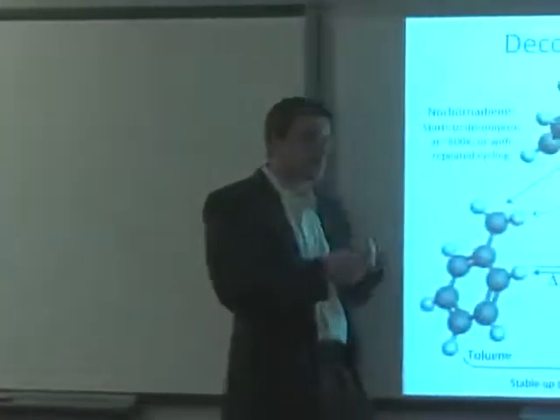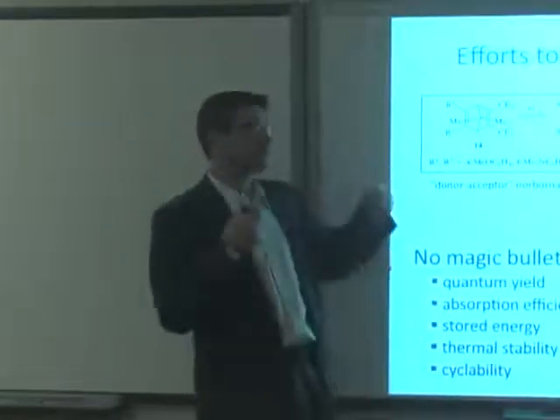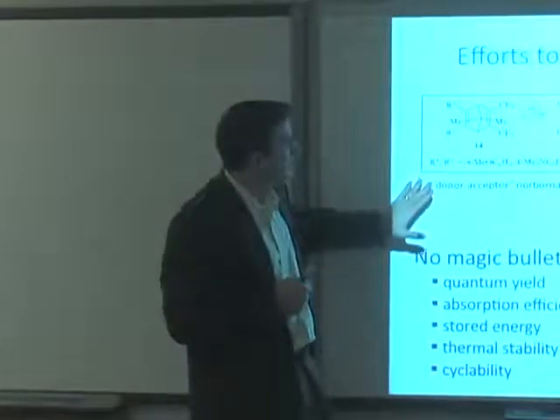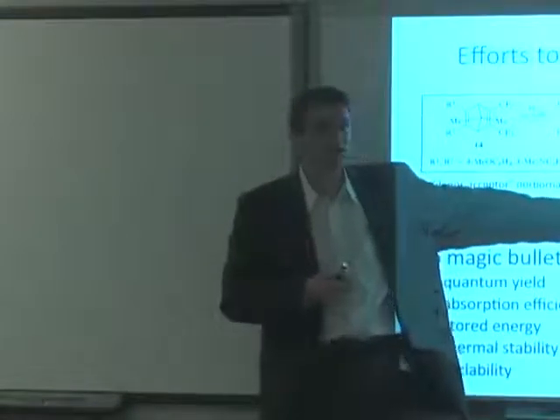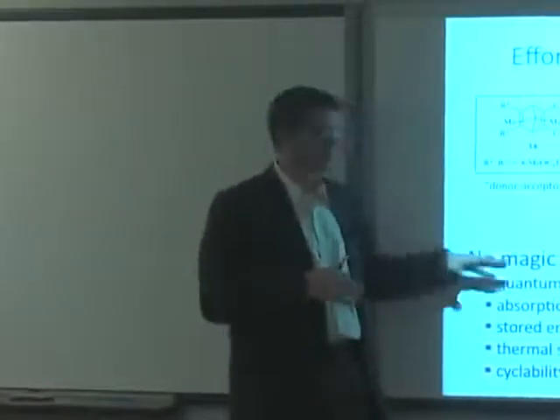And many substitutions were made. Metal atoms were substituted in the system. Different ligand chemistries were tried. Push-pull chemistries were attempted. And actually, at the time, the cyclability was increased substantially, from, say, 50 cycles to 1,000. The problem is that no matter what people tried, when you increase one really important attribute, you wound up making something else that was really important, like the quantum yield or the density, much worse. So no magic bullet was found.